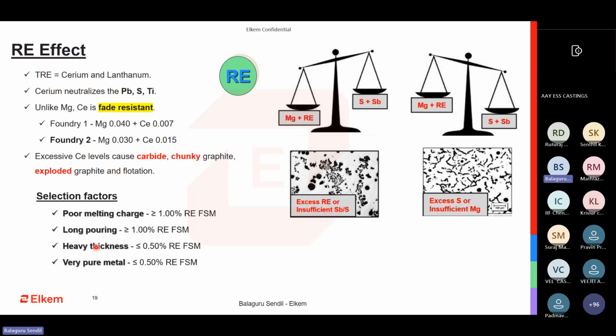When to use a less rare earth FSM is only when you are having heavy thickness, very slow cooling, very slow solidifying, heavy section castings, where the rate of cooling is very slow. Inevitably, the nodules are going to join together and form exploded graphite, or the possibility of chunky graphite is there. Then I go for a less than 0.5 or less than 1%, 0.1 rare earth FSM. Or when I have very pure metal, I know that the metal is extremely pure, I don't want to have more of nodularizing cerium and lanthanum. Then in that case, the possibility of chunky and exploded is high, so I don't go for it.